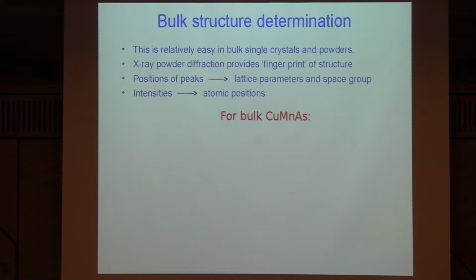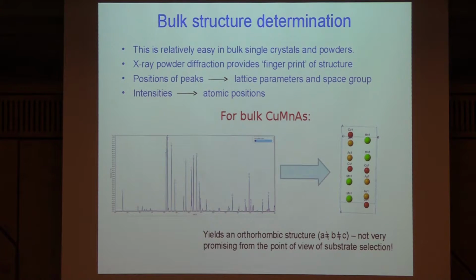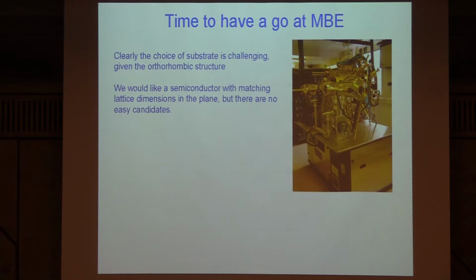Okay, so bulk structure determination, and it's a relatively easy thing to find out if you've grown a bulk structure what it is. So we just went through the normal sort of steps that you would do. You do some X-ray, you find a couple of peaks, and you can find the parameters, the space group, and the intensities give you some idea of the atomic positions. And for bulk copper manganese arsenide, it turned out it was orthorhombic. Okay, A not equal to B, not equal to C, not very hopeful for growing epitaxially. Okay, because we were quite worried about this, as you might imagine. So very, very difficult from the point of view of substrate selection.